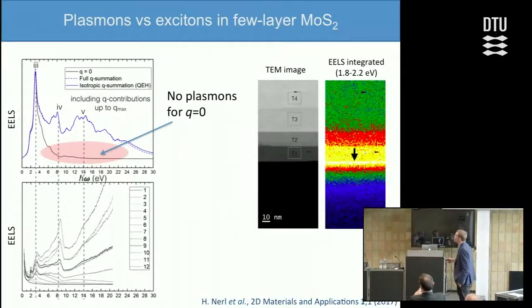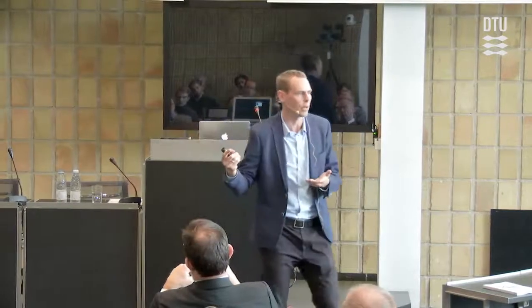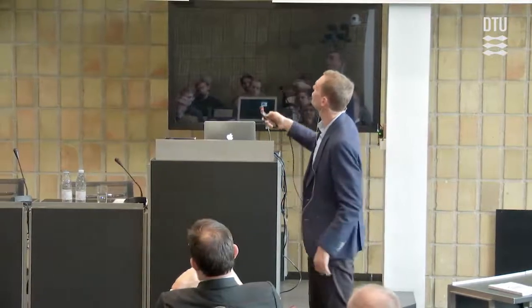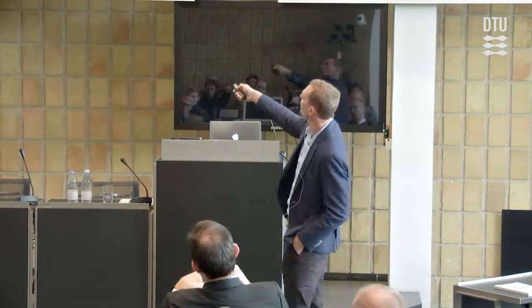There is another interesting thing here: for small Q values, that is slowly varying fields, they can only couple to the excitons, whereas rapidly varying fields couple to plasmons. And you can actually see that if you look at the EELS spectra here.